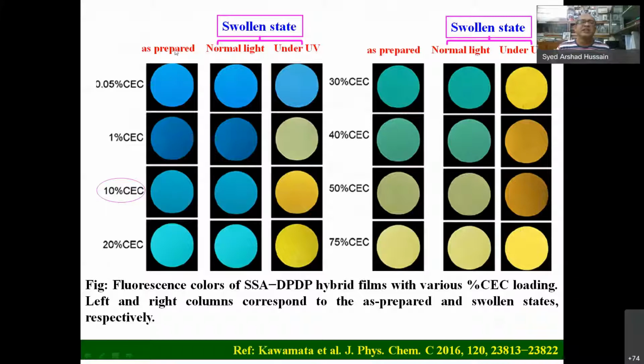Okay, so this is the photographic image taken with just a simple camera. This one is as prepared. Then what we did, we put a drop of some solvent. We use DMSO and we make it wet, that is, it is swollen. I told you that one important property of clay is swelling. Then we observe with normal light, and you can see no color change. But when we expose the swollen film under UV, you see the color change. This is for different concentrations of clay. You see the color change upon UV, but in normal light it's the same.